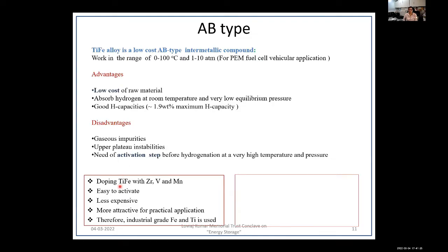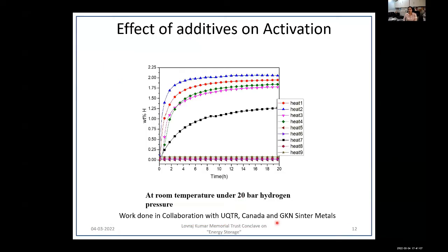Now what can be done is we can dope it with various other dopants in small quantities such that it can be made easy to activate. At the same time, we can get many practical applications using this particular alloy, and we can even use industrial grade materials. This alloy we have extensively studied. We have seen what the effect is if, instead of stoichiometric, we go for a non-stoichiometric composition. What if we substitute one of those? What if we add a catalyst?